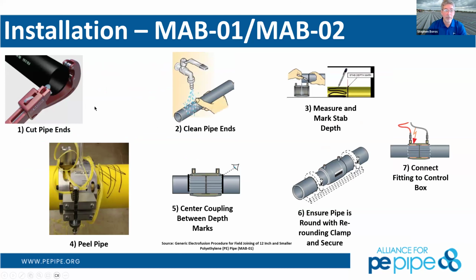Very quickly, these are the steps. Cut the pipe ends. Clean the pipe ends. Can't stress this one enough. This is the first cleaning step. Mark the stab depth of your pipes. How deep does it need to go into that coupler? Then you're going to scrape or peel the surface off. That's going to give you a nice clean surface that the electrofusion coupling is going to bond to. And this is a very key part of that. Then you're going to make sure that when you stab it to the mark depth, you're going deep enough to get full stab of those couplings on both sides.